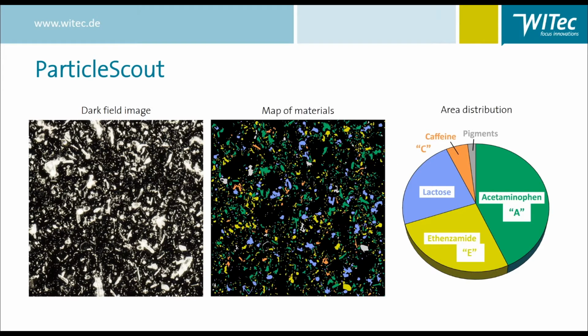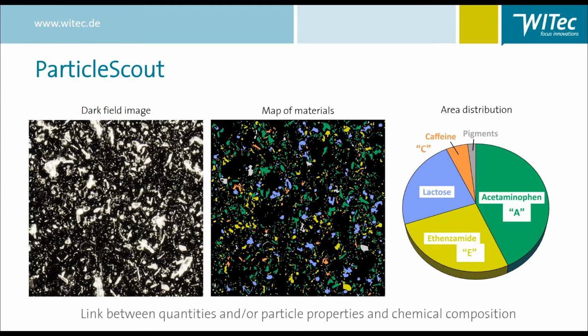The measurement revealed that the majority of the particles were the analgesic agents A and E. Caffeine was present as an effect enhancer, lactose as a carrier, and white pigment was also detected. A quantitative report describing the proportions of the substances found in the sample and their distributions in relation to size was then generated. This example shows how particle properties and quantities can be correlated with their chemical composition.